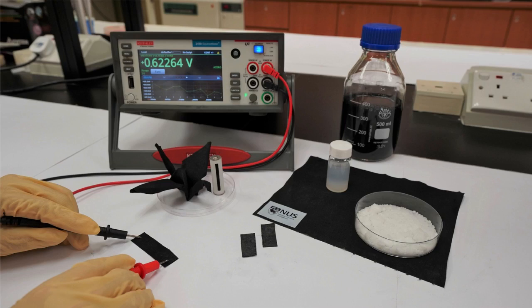Using a unique design of wet-dry regions, NUS researchers were able to maintain high water content in the wet region and low water content in the dry region. This will sustain electrical output even when the wet region is saturated with water. After being left in an open humid environment for 30 days, water was still maintained in the wet region, demonstrating the effectiveness of the device in sustaining electrical output.